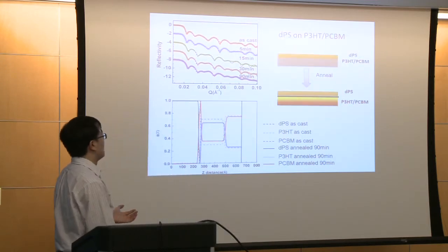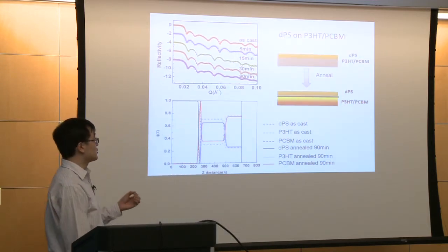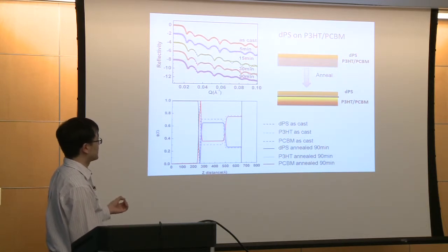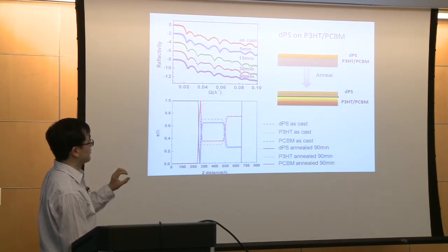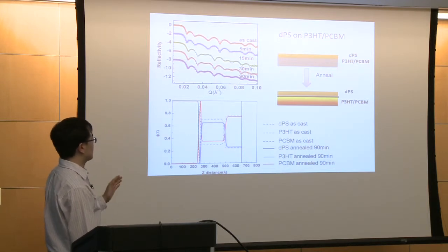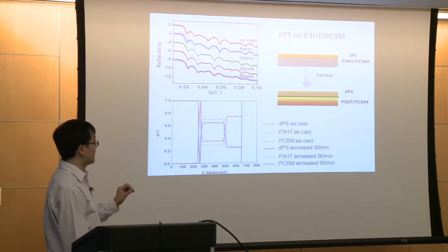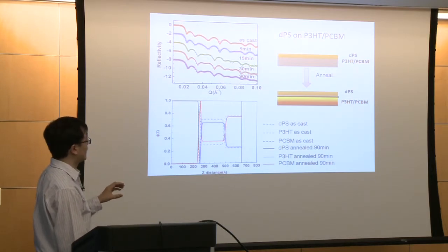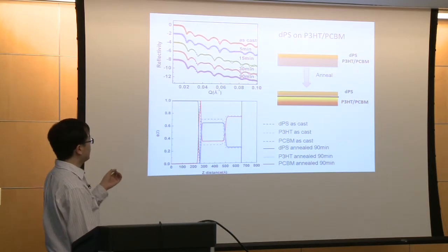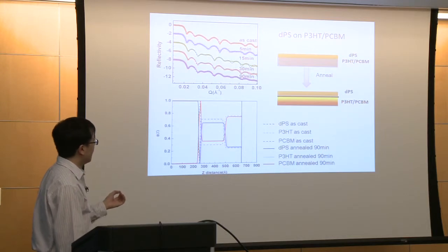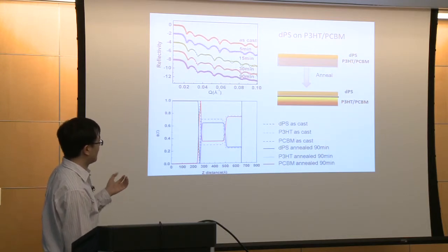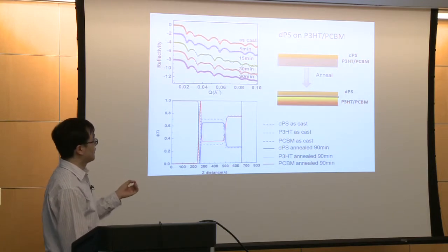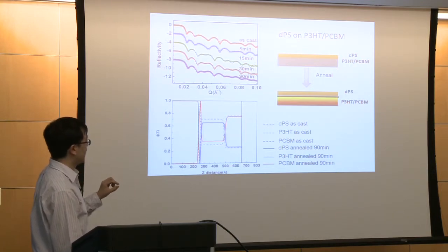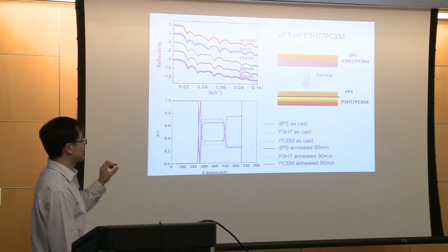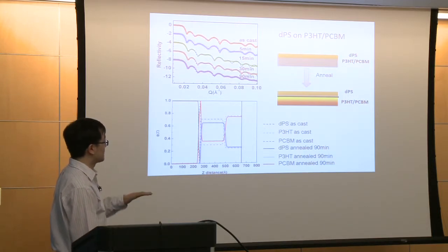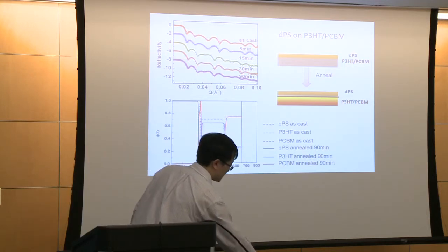We're also wondering, if the PCBM is initially located in the P3HT phase, whether the PCBM goes back to the polystyrene phase. So we do this experiment. We use a P3HT PCBM blend film as the bottom layer and the deuterated polystyrene as the top layer. And we find after 90 minutes of annealing, no PCBM goes back to the deuterated polystyrene phase, but a very thin layer of PCBM aggregates at the interface between those two polymers, while most of the PCBM stays in the P3HT phase.